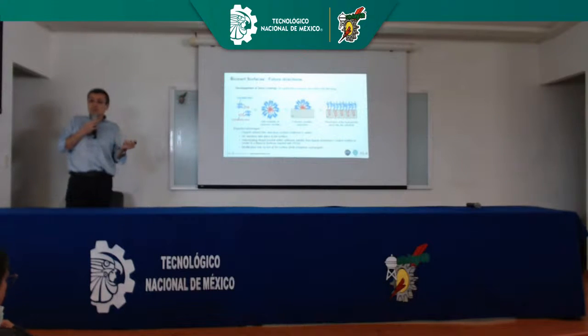What are the future directions for that? Okay, we are synthetic chemists. It was nice to work with chemistry, but there is some issue that you need to keep in mind. For instance, when you play with reactions, you have to use a solvent. The problem of chemistry is the solvent. So we were successful with some reactions because we were able to perform them in water. Water is not a big issue in terms of regulation. But when you start to use organic solvents, you start to swell the substrate, in particular plastics, damaging and reducing the mechanical properties. So that's a real limitation if you want to reach the patient, to find an application in industry. So the future is to avoid any kind of chemistry at the surface.